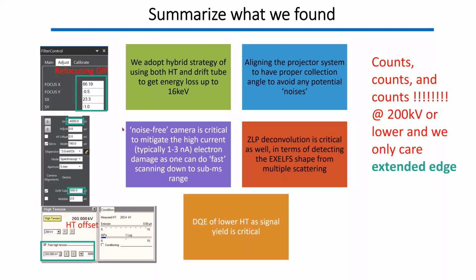Before talking about the counts for K-shell in EELS, we have to say that the strategy we are using to get the high energy core loss is a hybrid strategy, using both high tension change as well as the drift tube. With this hybrid strategy, we can get energy loss up to 16 keV, which gives a good signal to noise to judge. One can try higher, which we haven't tried yet, because we are more concerned about having good data quality, which makes sure we can interpret the data properly. So basically, if you want to get 16 keV, for example, you can go to 12 keV energy difference to change.